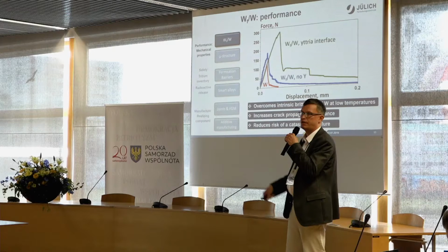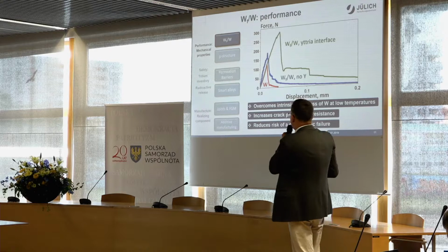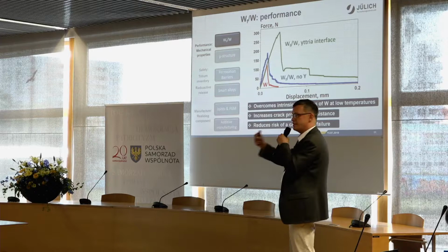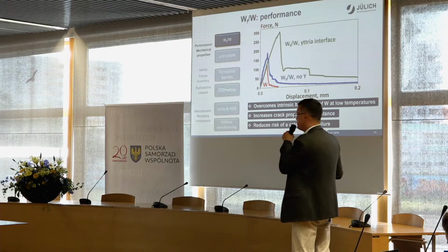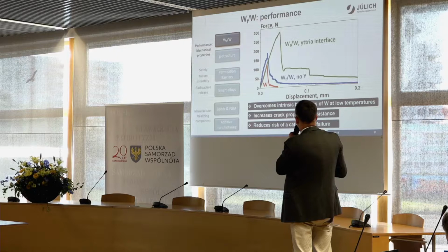If we have the first generation of tungsten fiber reinforced composites, which had only the tungsten fibers inside with this so-called strong interface, because they were very solidly built into the tungsten, you can see that first we're already reaching much higher force where it starts to degrade, and then it does not degrade till the end. So it really actually then fights here, so you can still apply the force until these fibers are pulling out.